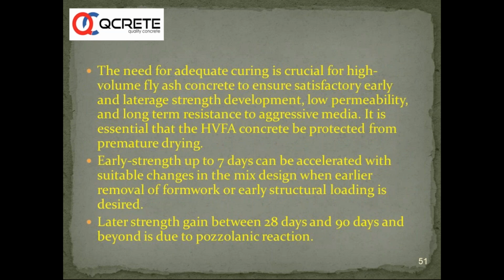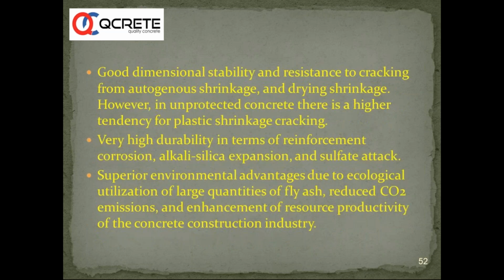As we already discussed, adequate curing is very, very crucial for HVFA. As we told already, the carbonation has to be taken care of. Carbonation will be an important factor. We need to cure it properly, and we need to reduce the water cement ratio to a very, very low level to have all the benefits from HVFA. Good dimensional stability, resistance to cracking from autogenous shrinkage, drying shrinkage. However, in unprotected concrete, there is higher tendency for plastic shrinkage cracks.